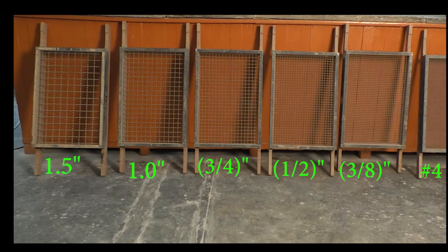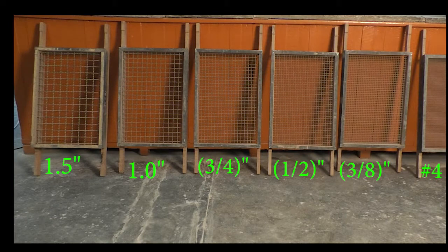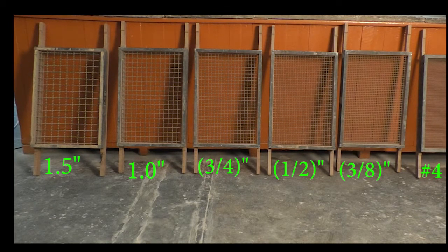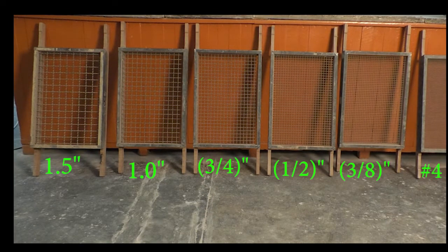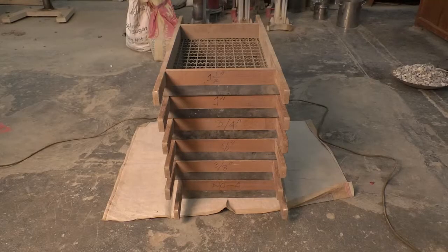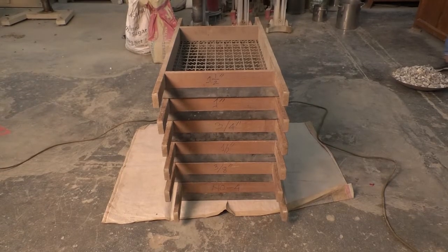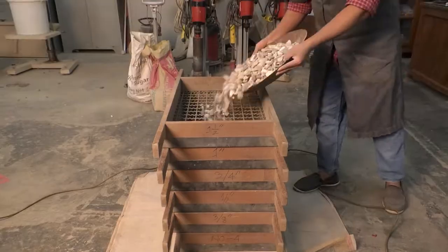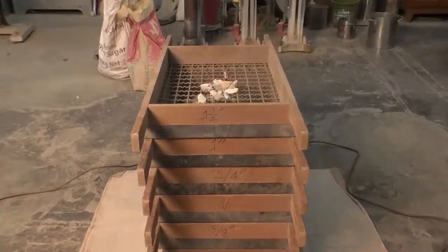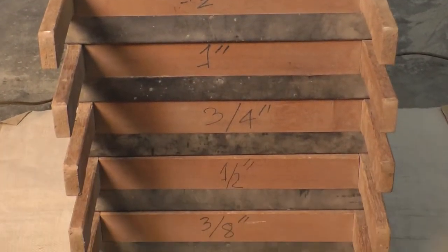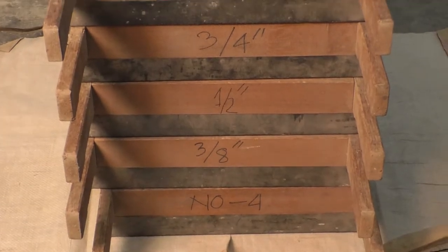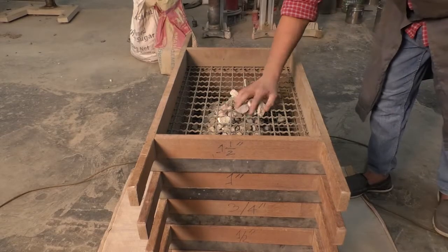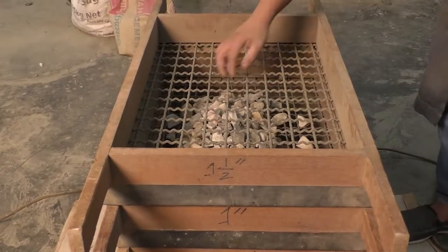Here it may be mentioned that non-standard sieves are sometimes used for smooth graph plotting and also sometimes used for specified practical uses. Now the sieves are nested in order of decreasing size of opening from top to bottom, and then the sample is poured on the topmost sieve. Since this is a 1-inch downgrade coarse aggregate sample, the full sample has passed through the 1.5-inch sieve.